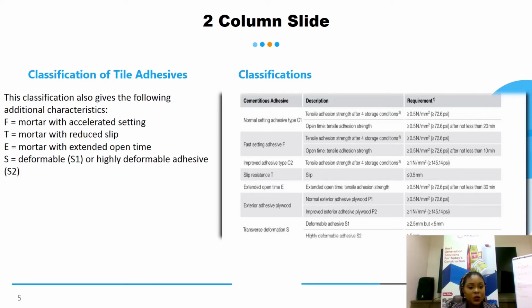And E, mortar with extended open time. What this does is it gives you enough room to make adjustments after placing your tiles. Naturally, when you're doing exterior facades, what you need is aesthetics, perfection. So when you place your tiles, it gives you a window of 30 minutes to be able to readjust, and arrange your tiles in place without destroying the tiles or the wall.